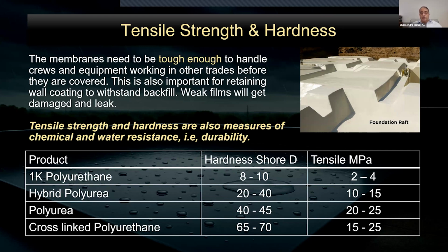The hybrid polyurea hardness is 20 to 40, still okay. Tensile 10 to 15, not bad. And the polyurea is 40 to 45 hardness, 20 to 25 tensile. Again, these are tough films. And the toughest is the cross-linked polyurethane, which is a 65 to 70 Shore hardness and a 15 to 25 MPa tensile. So the film must be tough. Otherwise, it will get damaged, as we've seen in the case of 1K polyurethanes.